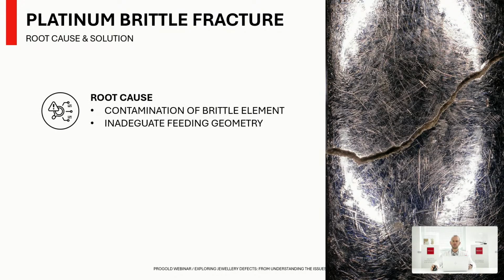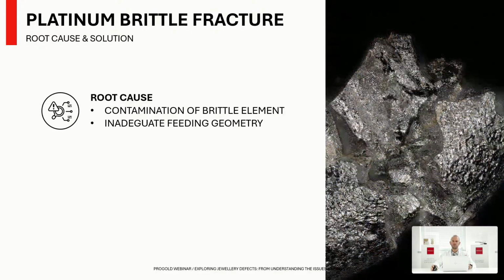What are the main causes of this defect? First of all, contamination by brittle elements could decrease the mechanical resistance of the material. But not only contamination, an inadequate feeding geometry of the model could also contribute to this issue.